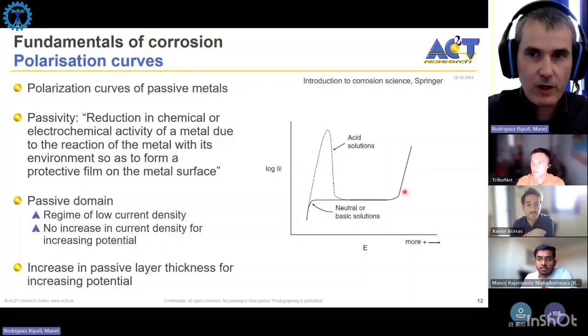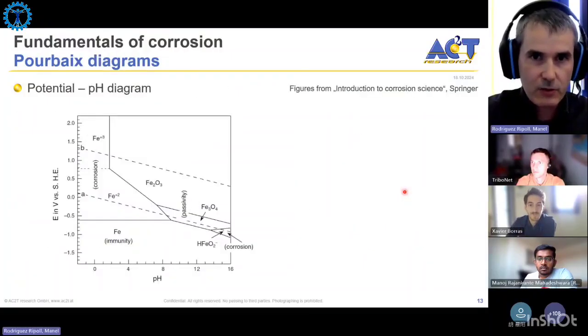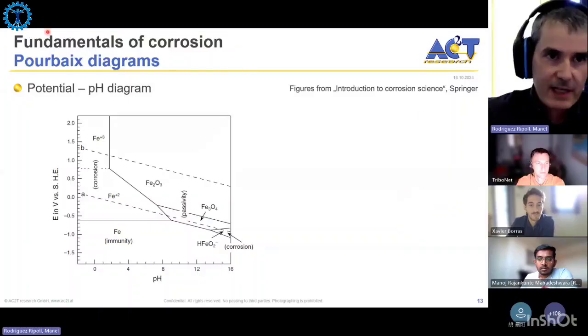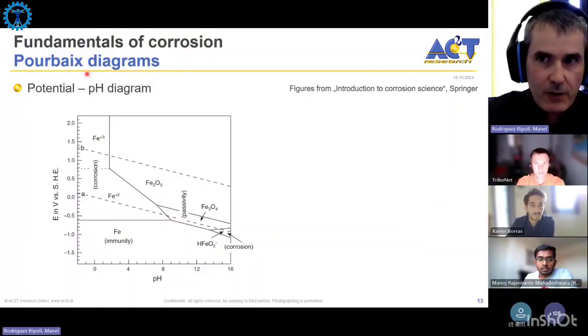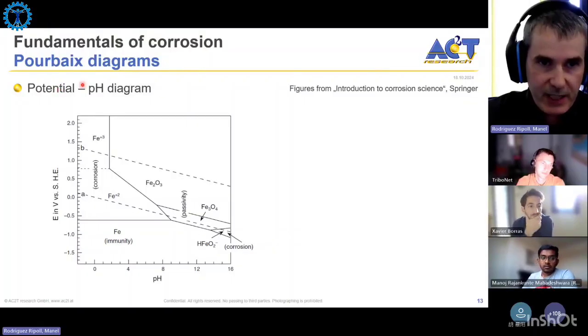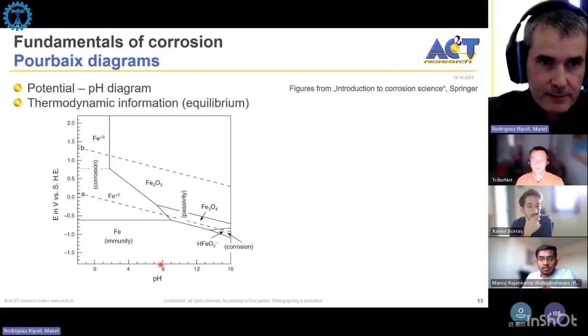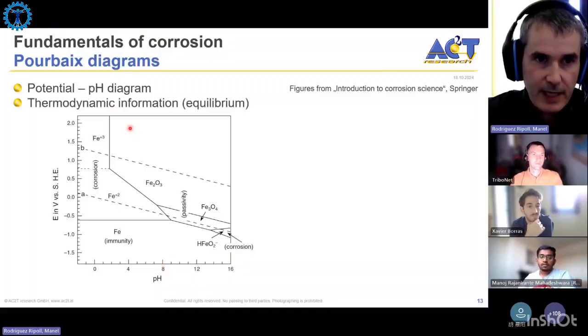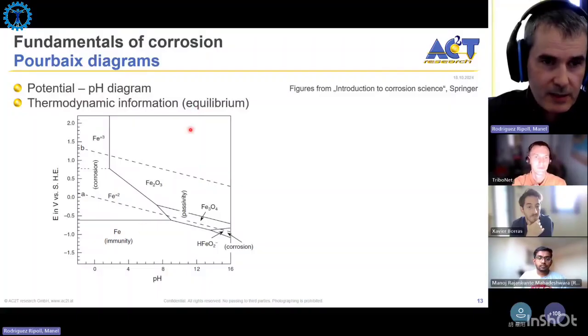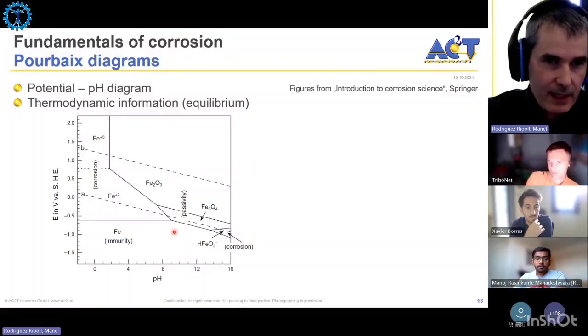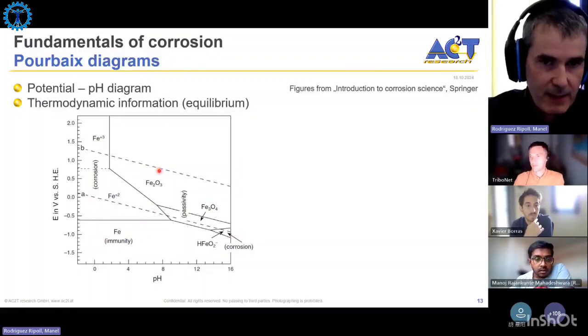But if we take into account only the thermodynamics, we can also have something called the Pourbaix diagram. This Pourbaix diagram is nothing but a potential versus pH diagram. In this case, the example is shown here for iron, and these are obtained under equilibrium. These diagrams tell us, for an applied potential or a certain open circuit potential, as a function of the pH, which chemical reactions or which chemical form will be favorable.